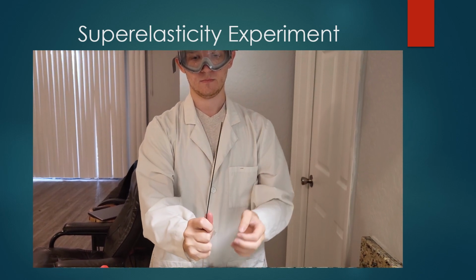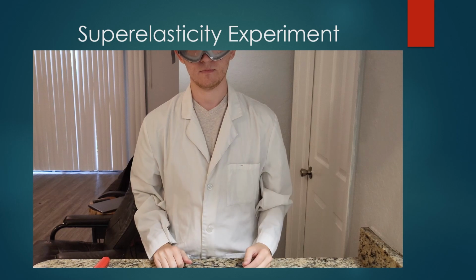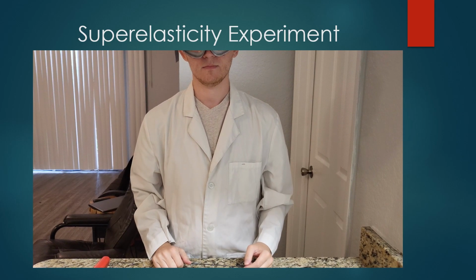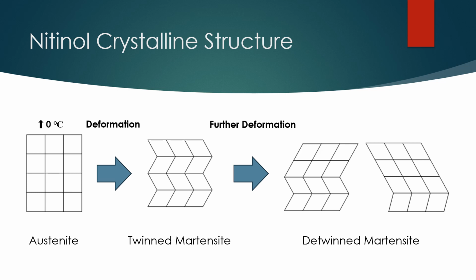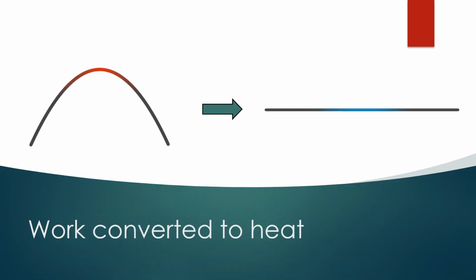experiment. A straight piece of nitinol wire is bent heavily, up to 30 times that of most normal metals, and is able to snap back in an instant. The mechanism behind this property is similar to shape memory, but instead the temperature at which the metal holds its permanent shape is set below room temperature, so that in normal conditions it's always in the austenite phase. Deformation therefore causes a phase transition to twinned martensite, then detwinned martensite, and once the stress is relieved, it transitions directly back to austenite. And due to the rapid set of phase transitions, the work done to bend the metal is converted to heat in the center of the wire. Undoing the bend then quickly cools the wire. Both of these temperature changes can be felt by hand.